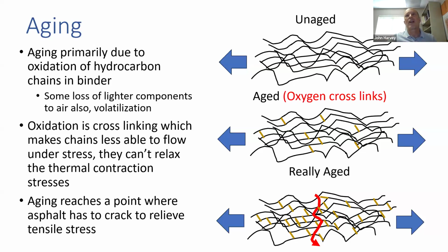Well, if we look at the top right here, asphalt starts out as hydrocarbon chains that can move fairly unencumbered, slowly, but it moves as a thick fluid. As time goes on, a little bit of the material that's in the asphalt goes into the air, called volatilization, but the main thing that is the process of aging is that as hot air gets into the asphalt, you start getting crosslinks, which we have represented here with the little gold bars.